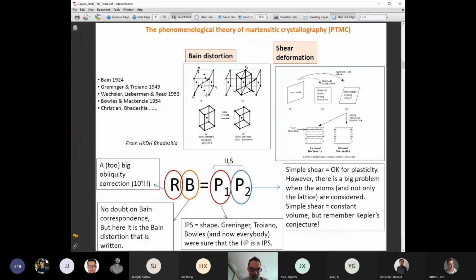volume change. But it's not enough, because if you just put a simple shear, you cannot make the equality with RB. So you need to add another shear that is called P2, another simple shear that represents stacking of dislocations or mechanical twinning inside the martensite and so on. Well, anyway, this is more or less the spirit of this PTMC, phenomenological theory of martensite crystallography. And one of the best promoters of this theory is, I'm sure you know him, Professor Bhadeshia at Cambridge University.